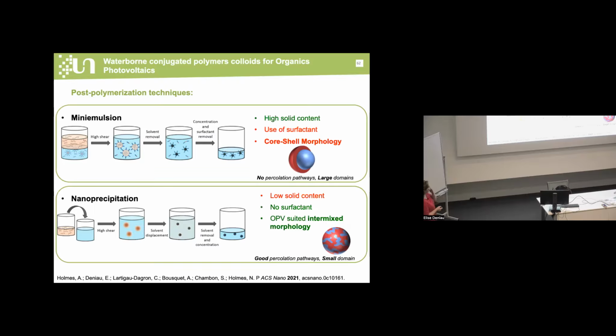And this is very important because this difference makes opposite limitation and advantage. While high, stable, high solid content of nanoparticles is obtained using miniemulsion, the use of surfactant makes this process not very friendly for the OPV application because of the insulating character of the surfactant. And also it leads to a core-shell morphology, which is not suitable for OPV because you need charge transfer.